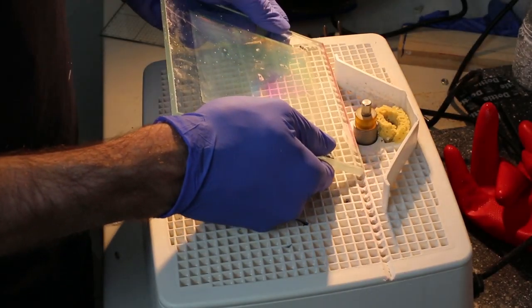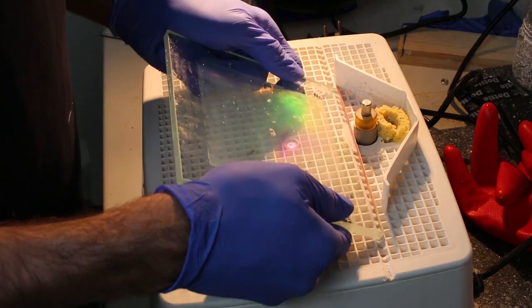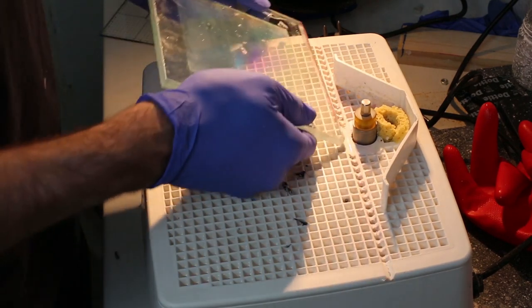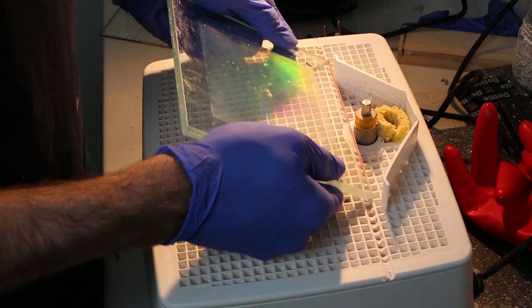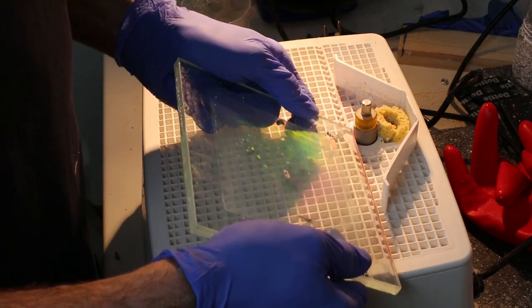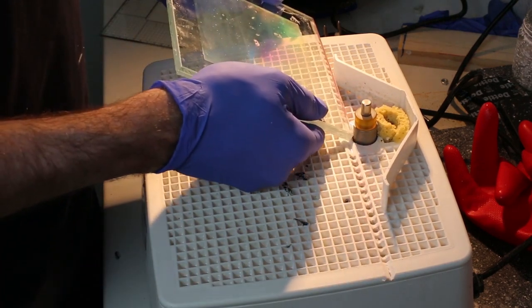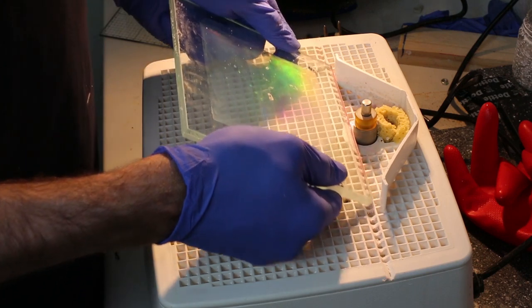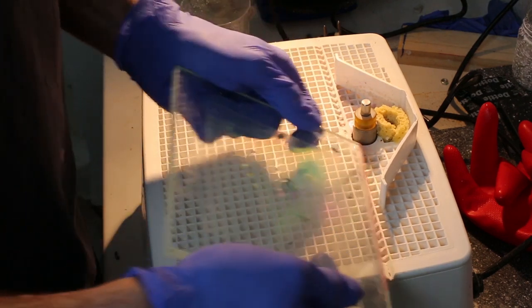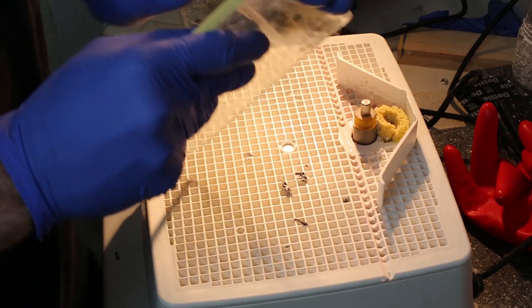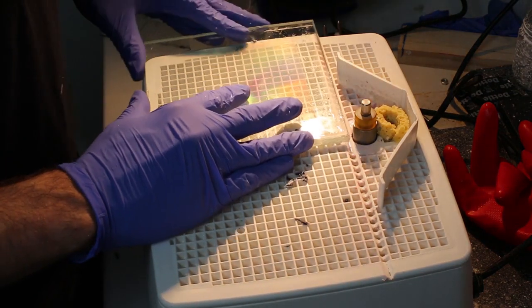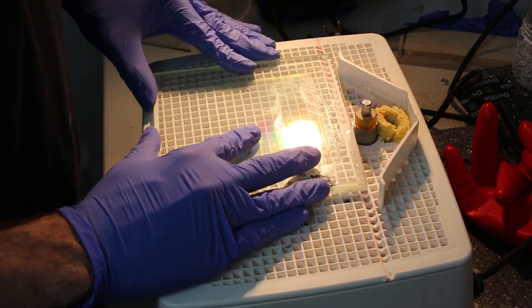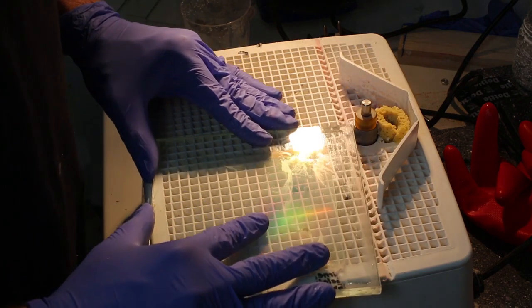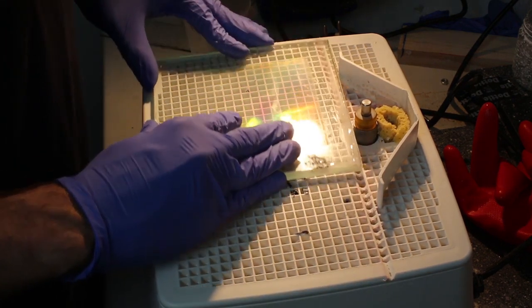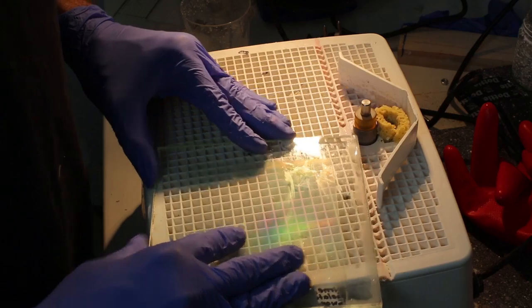When grinding the glass, you always want to grind the top and bottom edges first, while holding the glass plate at a 45-degree angle towards the grinding bit. This is called chamfering and will create a triangular shape. Only in the final pass will you level the plate by pressing it flat against the grinding bit, taking off the tip of the triangle. This will prevent the glass from chipping.